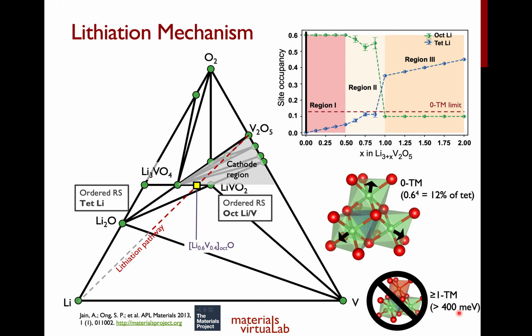Okay, so as we continue to lithiate, what we found was that when you insert this lithium into this tetrahedral site, due to electrostatics, where each tetrahedral site is face sharing with 4 other octahedral lithium, your lithium in the neighboring octahedral sites begins to displace a little bit. The displacement is about 0.2 to 0.3 angstroms. However, that displacement is still relatively small, so we still classify those lithium as being in tetrahedral and octahedral sites rather than some other coordination. So this accounts for what is happening in this entire region 1 of the intercalation process.